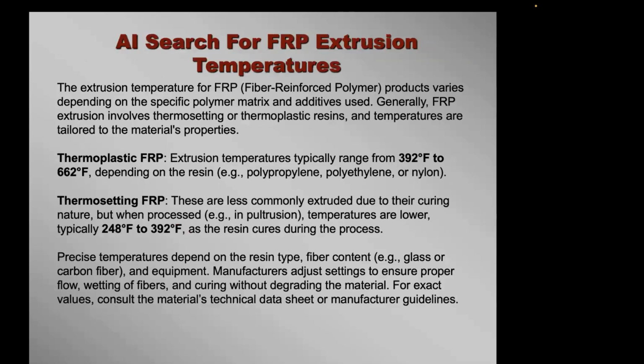But what's more concerning is that in order to make these materials in that profile, they have to get them to a liquid phase. So they have to melt at a certain temperature, and that melt temperature has to be below the burn temperature. Otherwise, you'll burn the material up. So your thermoplastic FRPs, that melt temperature, so they can get it through the Play-Doh fun factory of life, so to speak, is 392 to 662, depending on the resin. For thermosets, it's 248 to 392 degrees. So it's about half the burn temperature there. And it all depends on what's in there.